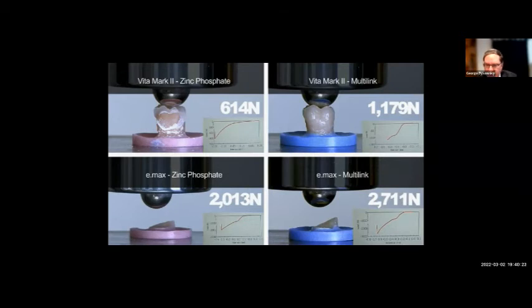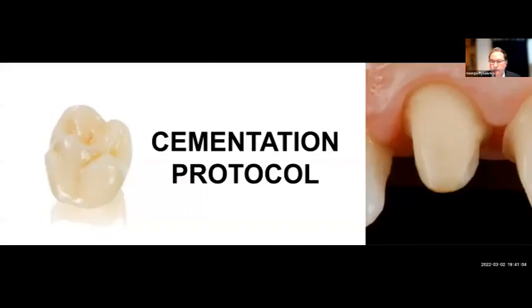And I want to keep in mind, there was a previous slide or video that I showed you of the same study where we had a zirconia at 0.5 with conventional cement, and the value was at 3800. So 600 for a weak, 1100, 1200 roughly for weak and strong. Strong and weak ceramic was about 2000, and then the strong ceramic and the strong cement at 2700. And if we use zirconia in that fashion, then it's even higher. So again, balancing the properties of cement, not only the material makes a proper result, but the cementation protocol has a significant influence in that direction.